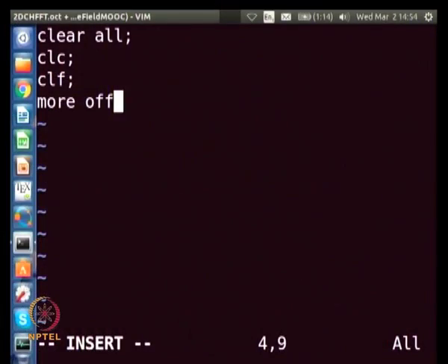Okay. So now what we are going to do, of course, we want to start with an initial profile. So let us say that we have some 64 points. Now here we have to say nx and ny, because there are two dimensions, x and y; if you have z, nz also you have to say. So let us say I take a square domain, the region where I am going to evolve my microstructure. So nx is 64, ny is 64.